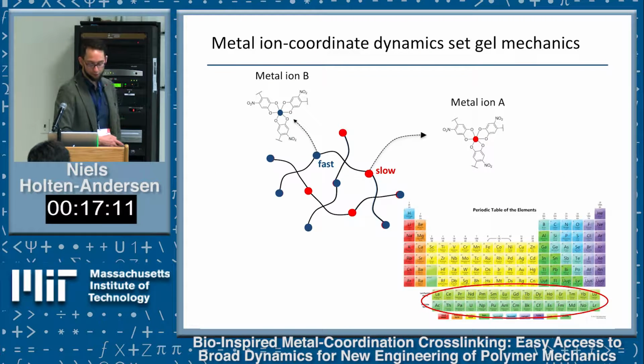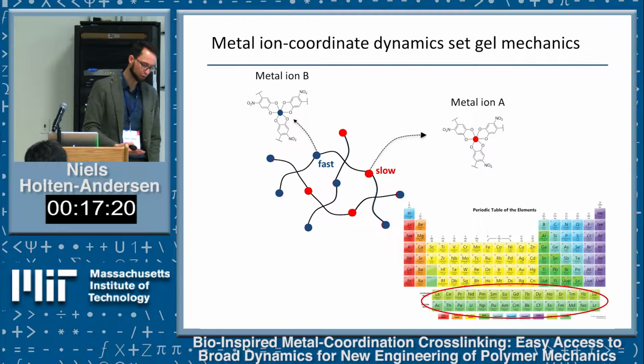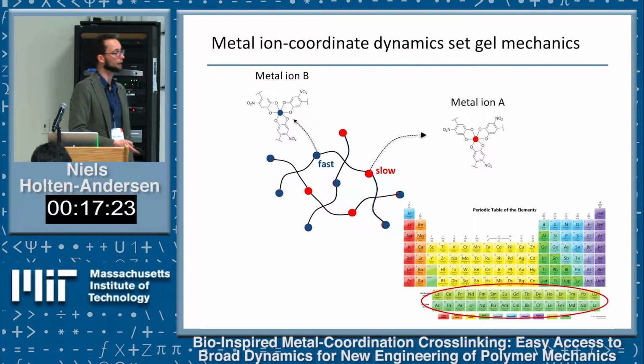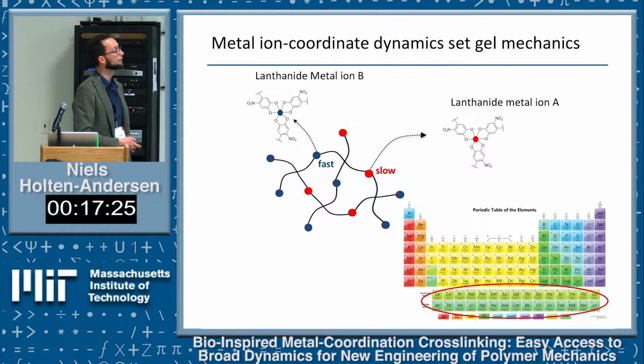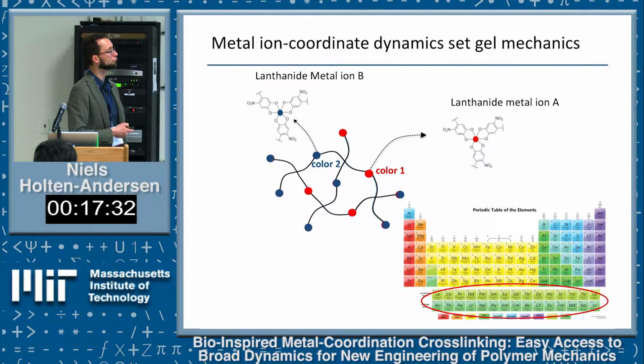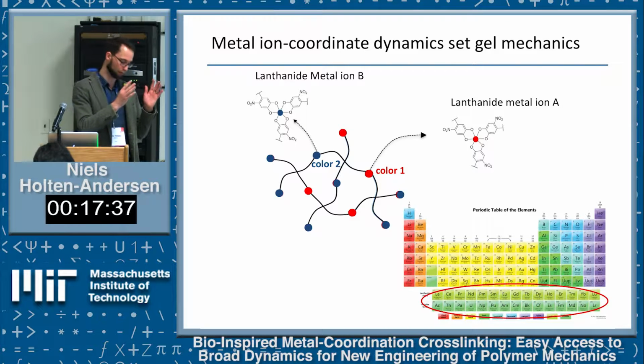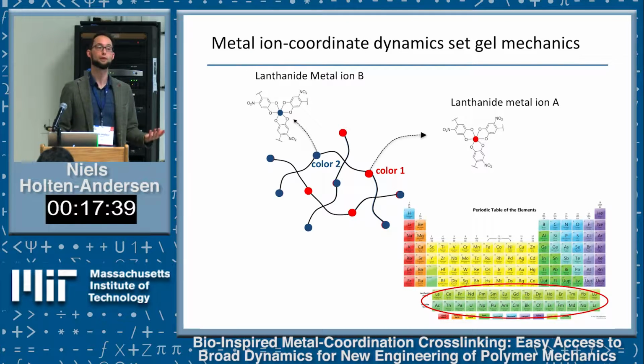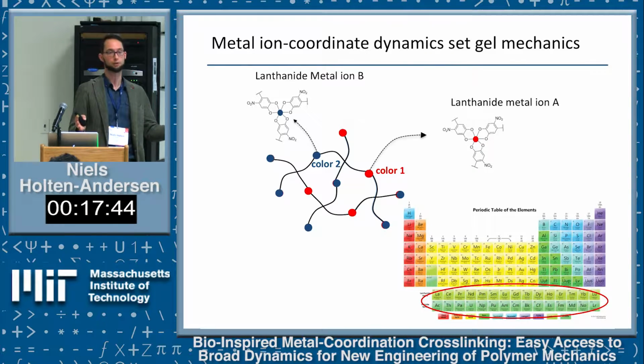Another thing we've been doing, as a demonstration of how we can play tricks with these chemistries, is using some very exotic rare earth metals called lanthanides, down at the bottom of the periodic table. There's been a lot of work showing that if you use lanthanides as your cross-linking species in these metal coordinate crosslinks, you get fluorescence. If you excite these crosslinks with typically UV light, you get fluorescence as a function of which lanthanide ion you use, so you can tune the color the material emits.